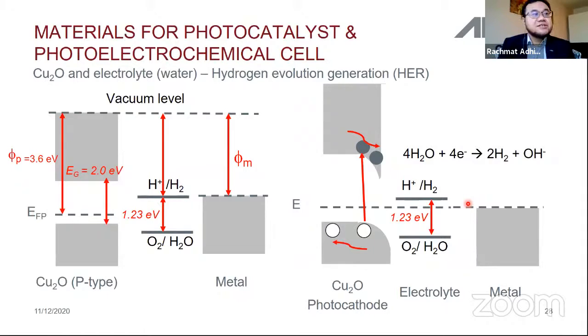So here, in the case of cuprous oxide, let's say, because we are working with cuprous oxide, the cuprous oxide and water simply follow the previous picture. Once light comes to your semiconductor, your cuprous oxide, the electron is excited into the conduction band. It goes down because the energy level of the conduction band here is lower. And then the electron will reduce the water into hydrogen, and you see the hydrogen bubble there.